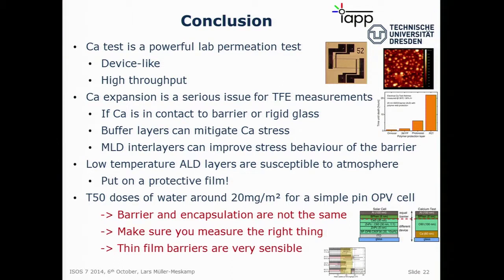And we also do this for all our aluminum electrodes. It really improves your measurement results a lot if you put a piece of PET on top. And then these T50 doses of water are around 20 milligrams for this specific system. It's not true for all solar cells. There's some more stable stuff around. But for this intrinsic system and this aluminum interface, it's very sensitive.